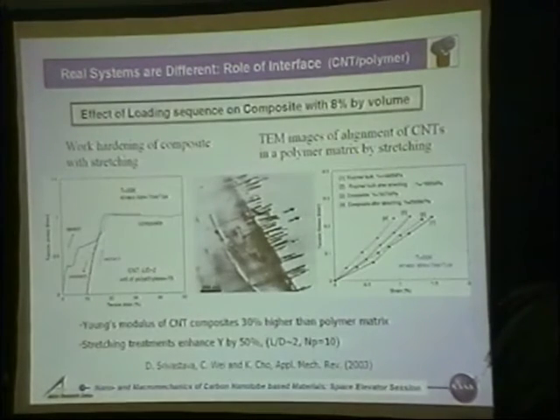I'll not go into this part. So the second part is that, if I somehow can interlink these tubes in those bundles, I can increase their stretching modulus, tensile strength, all those things. Remember that tensile strength is related to the stretching modulus by just the strain value at which it will break. If it's 5%, 10%, you just take that number. That's why I showed you in the beginning. And this shows you the example.